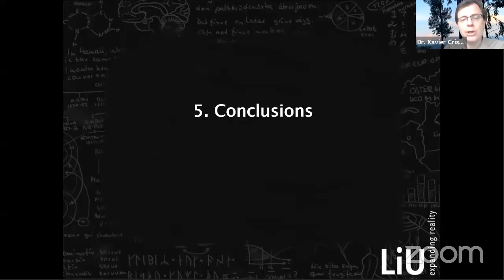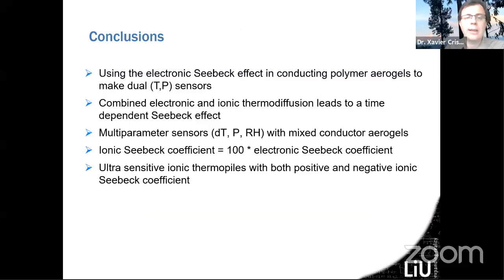So just to finish as a conclusion: we have been using the electronic Seebeck coefficient in conducting polymers to make aerogels to create sensors for temperature and pressure. When we look at humidity and use ionic charge carriers, we can also have the reading of humidity. And then we use the ionic Seebeck coefficient, which is 100 times the electronic Seebeck coefficient, to get super high thermopile voltage for the first time. So thank you for your attention.